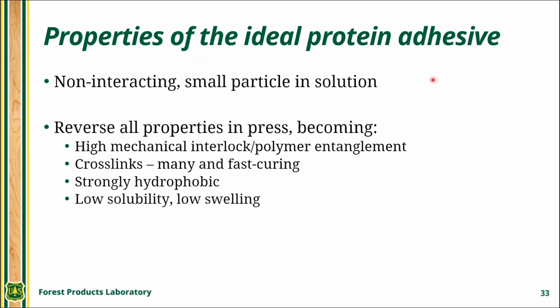So what are we actually looking for? Okay, we want low viscosity, so no non-interacting small particles in solution. We want mechanical interlock, polymer entanglement. We want crosslinks. We want many and fast curing crosslinks. I don't believe there's any kind of panel adhesive system out there that you can count on more than 2 minutes at 100 C is the maximum you're going to get. 1 minute at 100 C is a more realistic number for how much time and temperature you're going to get to cure your adhesive. So these crosslinks have to be fast, strongly hydrophobic, and low swelling.